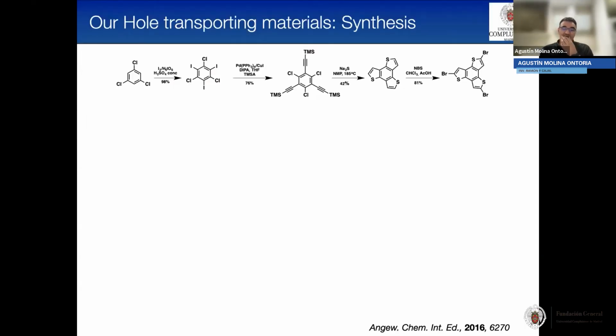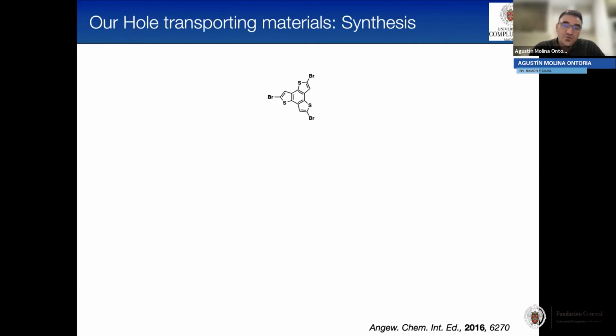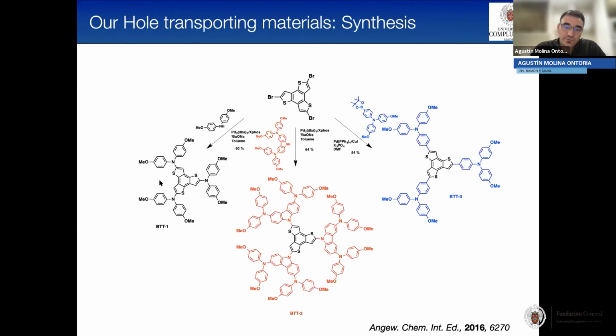So the synthesis of these molecules started with this trichlorobenzene. We performed a 3-fold iodination reaction followed by a 3-fold Sonogashira cross-coupling. In order to close the ring and form the thiophene rings, we used sodium sulfide in refluxing NMP, and finally we brominated at the alpha position of the thiophene. Finally, to introduce the different electron donor groups, for BTT1 and BTT2, we performed a 3-fold Buchwald-Hartwig reaction. And in the case of BTT3, we performed a 3-fold Suzuki cross coupling.